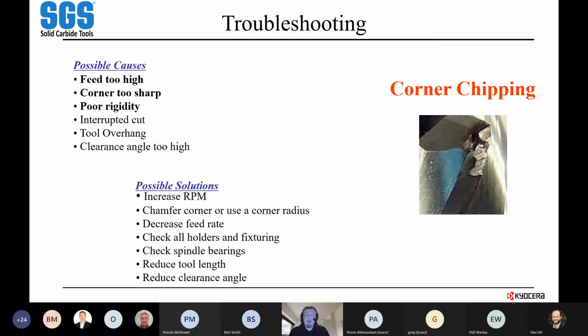If that's not an option, then like I said, you can play with your RPM, lower your feed rate, get that chip load down, make sure that all of your setups are rigid. If you have an interrupted cut, then slow down going into that interruption. Really, if it's an extended amount of interrupted cuts, then you may just slow down overall and allow it to engage those interruptions a little bit more efficiently.